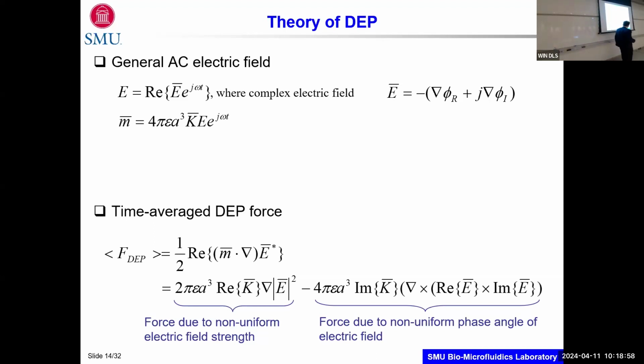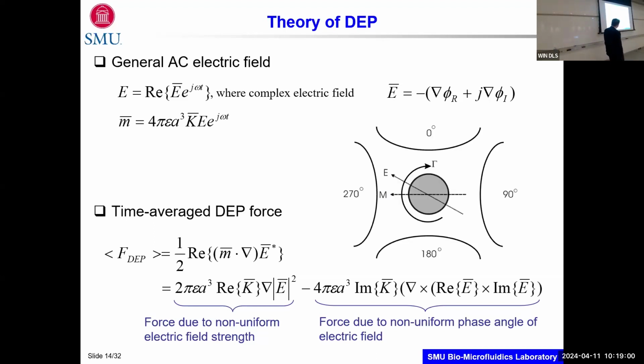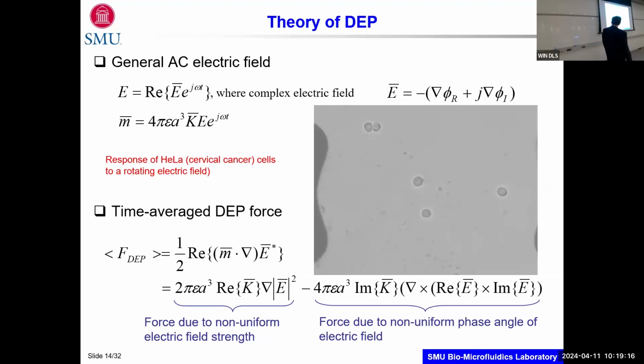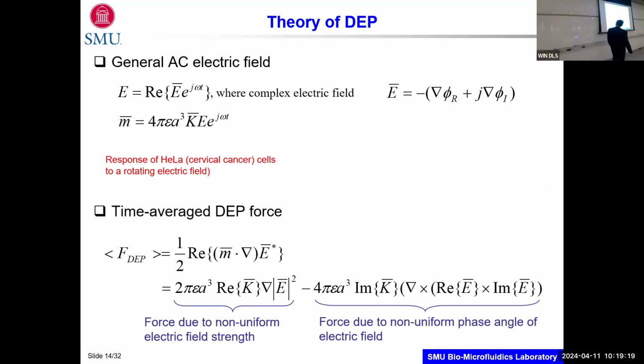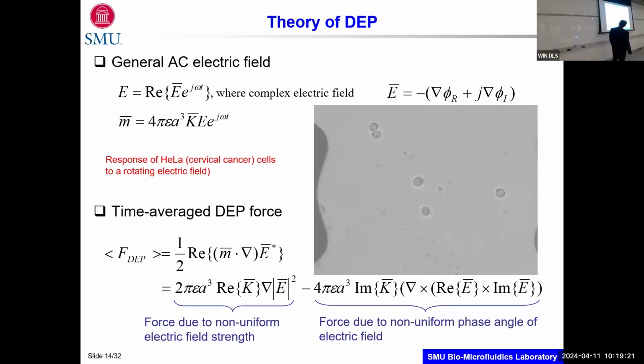Too many imaginary and real numbers there. So what we have done, like others have done too, is that we create a 4-electrode system. And then if a polarizable particle is in there, and you put an electric field with a phase angle, you can induce a torque on those particles. So the movie here shows response of cervical cancer cells to a rotating electric field.